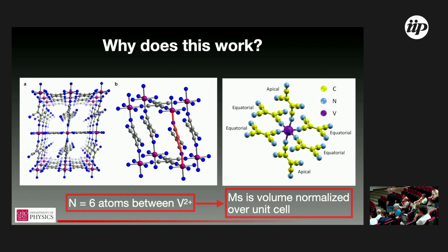I don't know if I would dignify it with the label of theory. It's a bit hand wavy, but this is what I was trying to allude to here: you have a single electron state that's highly delocalized across that red line. That leads to very strong next nearest neighbor exchange coupling, or antiferromagnetic exchange, between 3/2 vanadium, minus 1/2 TCNE, 3/2 vanadium. So the energy scale along that direction is very high.